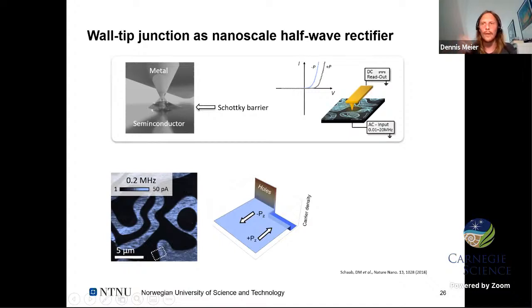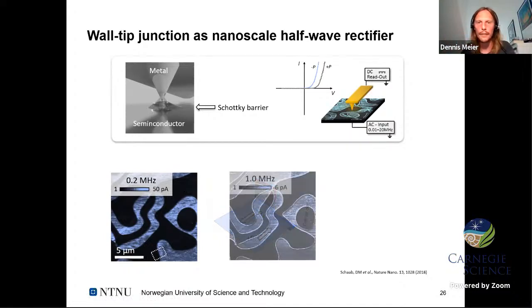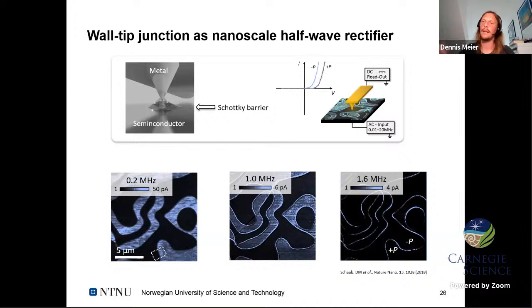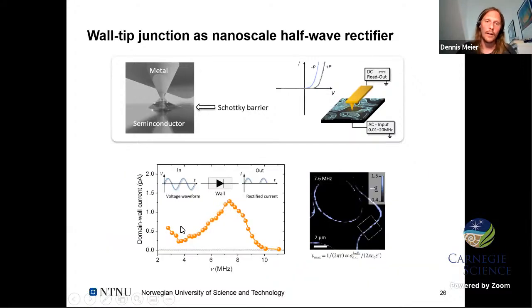What's interesting now is if I ramp up the AC frequency, if I go to higher frequencies, you see that the domain contrast gets worse, and I'm left at high frequency with the contrast at the domain walls. So there is one regime, when I go to high enough voltages, where only the contact with the domain walls has this rectifying behavior. Here you see now up to what frequency that works. At a frequency of about 10 megahertz, also the domain walls stop rectifying, and you go to symmetric behavior. So we send in an AC voltage, and what we get out is a rectified current.